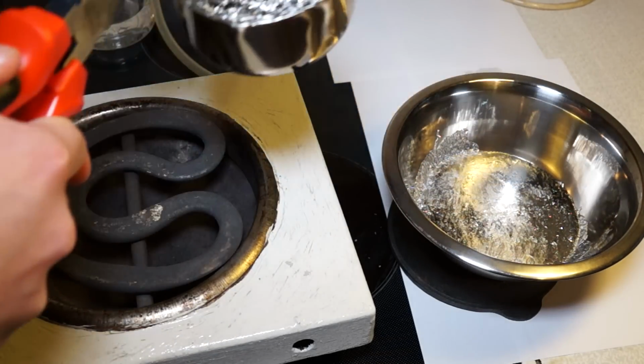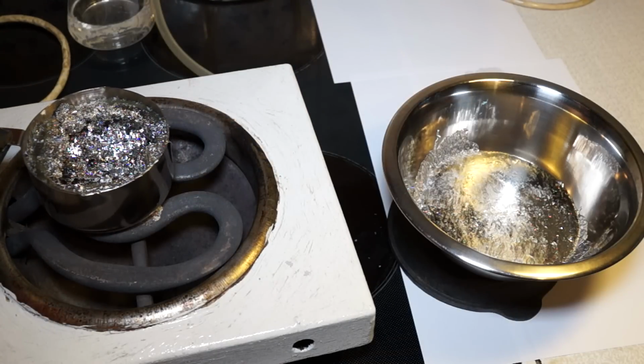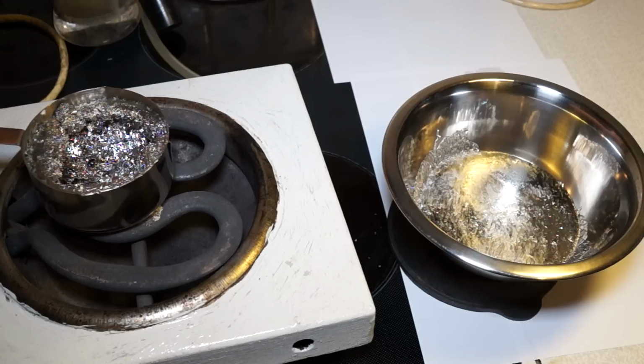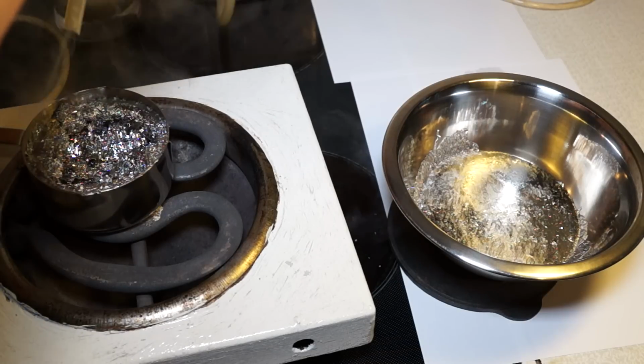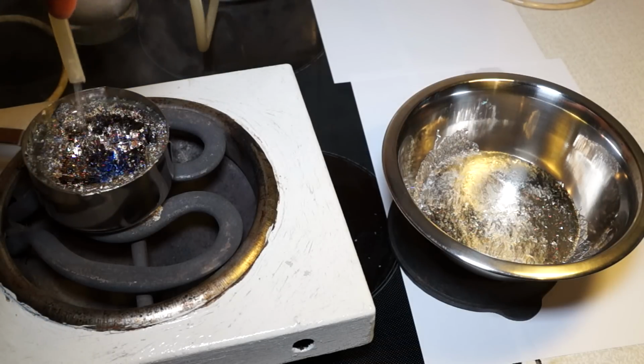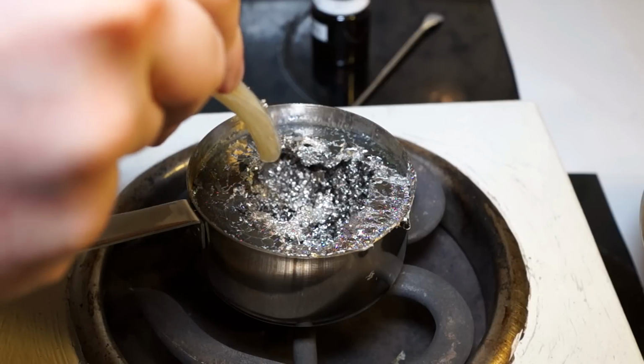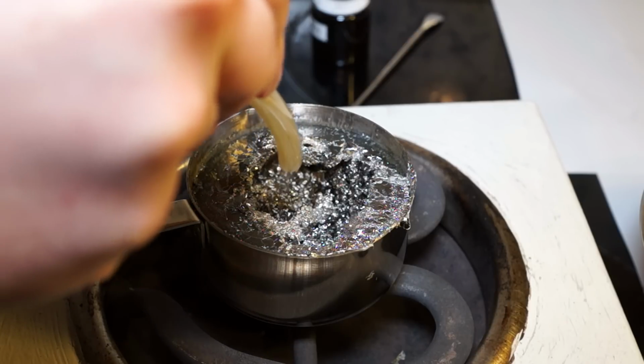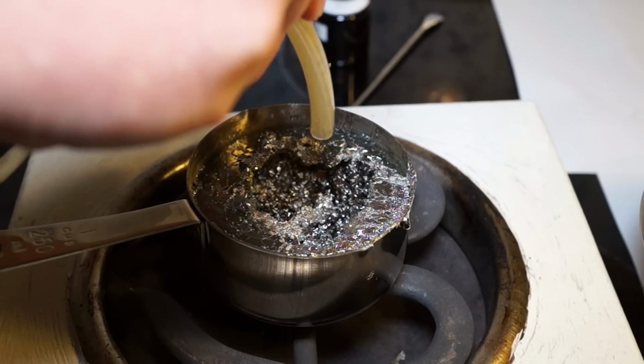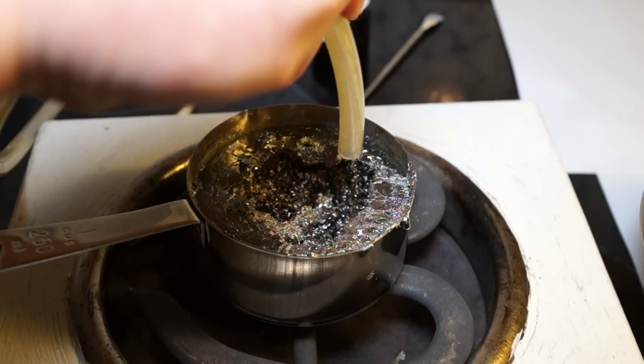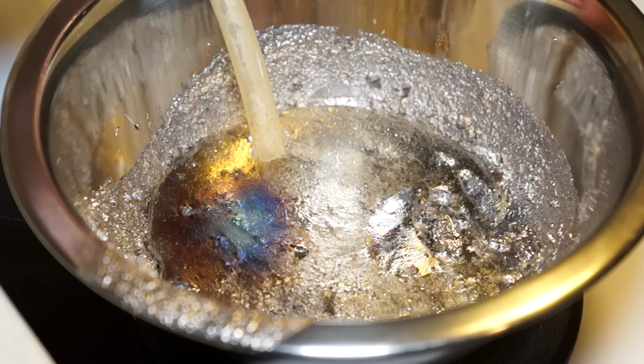If it was a pure bismuth, the hot crystals on air would have begun to cover with a beautiful oxide film. My bismuth has a lot of lead impurities, and on air the film of oxides does not form. To make the crystals colorful, I'll apply a current of pure oxygen on our hot crystals. I get the oxygen from the decomposition reaction of hydrogen peroxide.